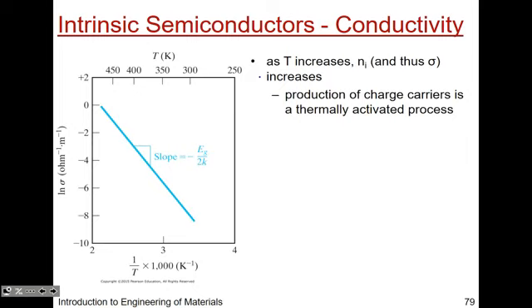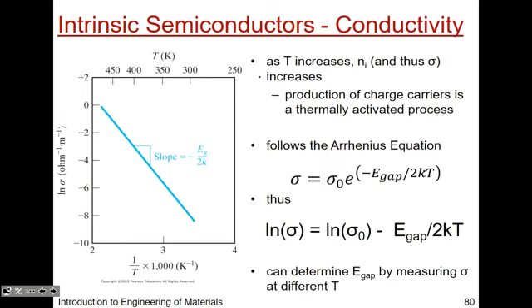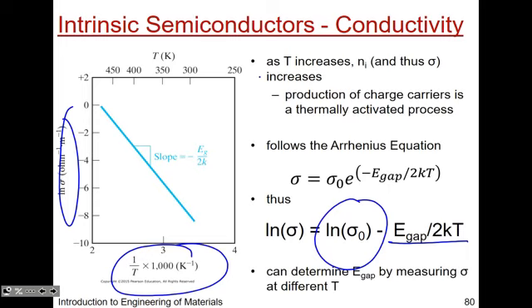Again, you'll never stop seeing this, by the way, in your life. In fact, the default answer, if you had to guess, is that it's a thermally activated process. It's like guessing that your crystal structure is monoclinic. You'll be right about 72% of the time, okay, for any known material. Okay, so this relationship you've dealt with, you've manipulated. This equation is something you know and love, right? You have conductivity, you have some materials constant, and you have the 1/T relationship. Log of conductivity, reciprocal temperature. You can backtrack out the band gap pretty easily, okay?